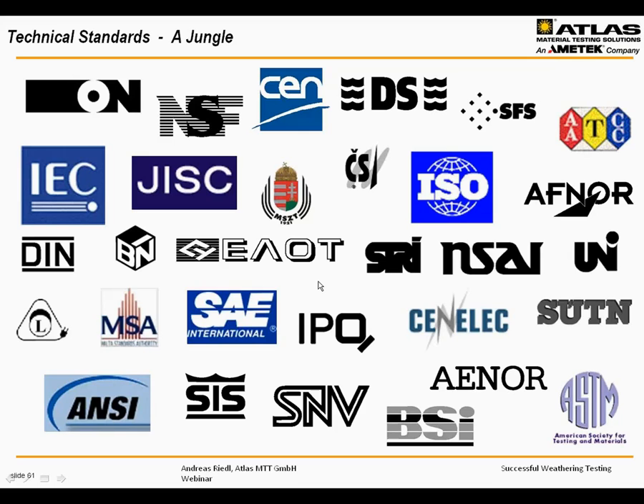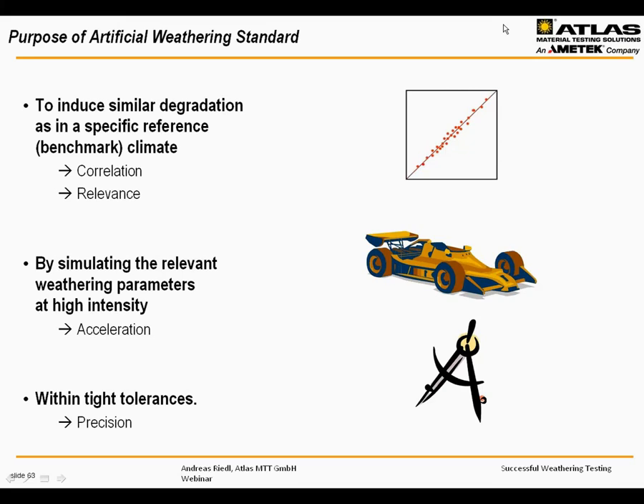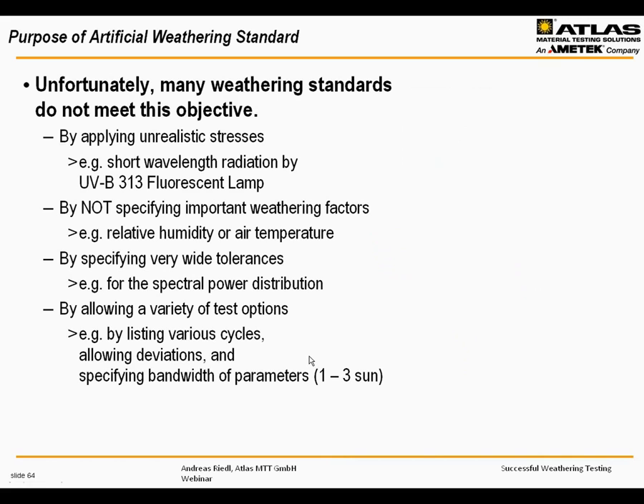The purpose of an artificial weathering standard is actually always to induce similar degradation as in a specific reference climate by simulating the relevant weathering parameters at high intensity, but not too high, within tight tolerances. And this leads to what we discussed before: correlation, relevance, acceleration, precision. This is the basic framework for an artificial weathering standard, but unfortunately many of those standards do not meet these objectives. You can't say from the first glance which standards do and which don't, but there are older ones, and only those who were active in the standards committees and know what was decided know why a specific wording is in the standard. Normally to satisfy a certain